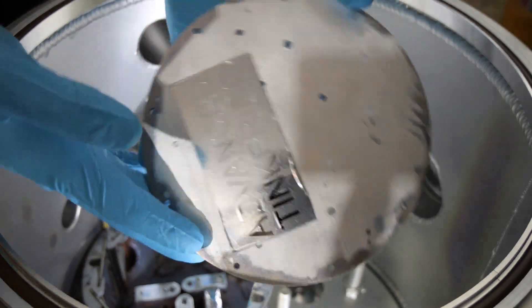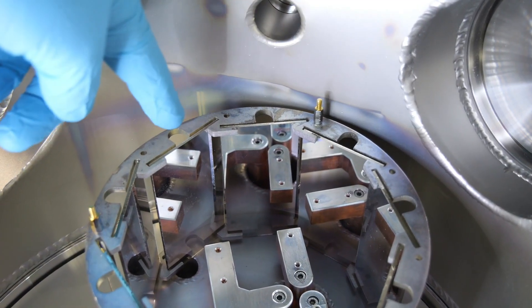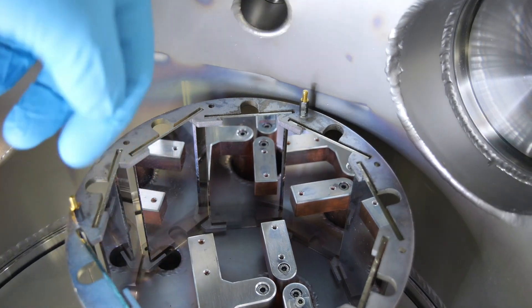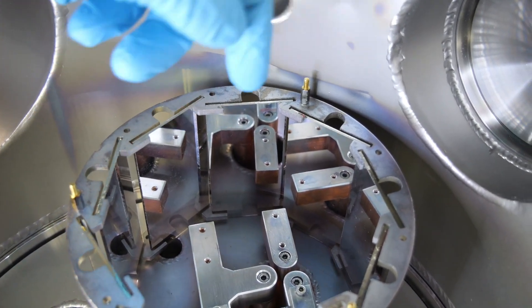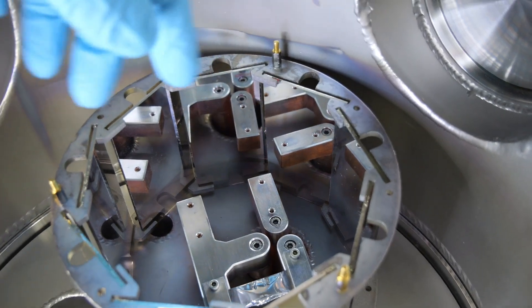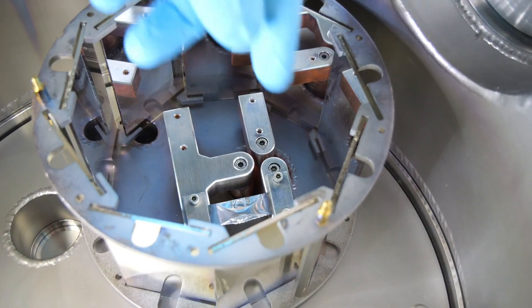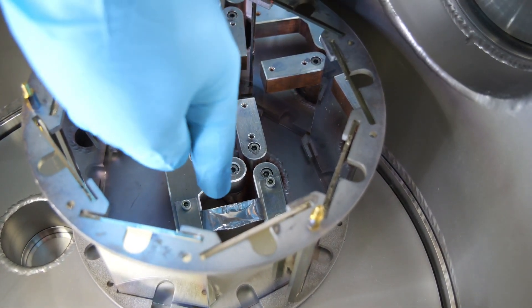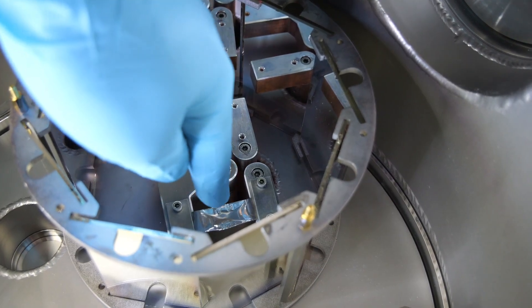Looks like the vinyl survived. And well, looks like my construction to protect the chamber didn't work perfectly. I think the reason is that I just assumed the metal source would be in the middle. And well, it's not. And that's why there are gaps in line of sight with the evaporating metal.